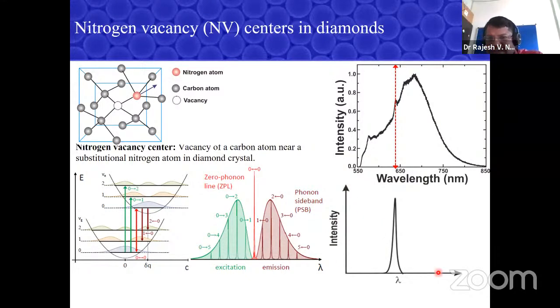And why do you need a spectra just like this? If you look at the ground state and excited state of a nitrogen vacancy center, we have an electronic ground state and excited state. There are many vibronic levels. And if we excite this with a laser, you have a transition from 0 level to 0 level, that is the 0-0 transition, without involving any vibrational quantum number or without any phonon induced transition. So this red transition, which is the 0-0 line, is a pure electronic transition, and there's no dephasing induced by the phonons. And this corresponds to 637 nanometer in this.